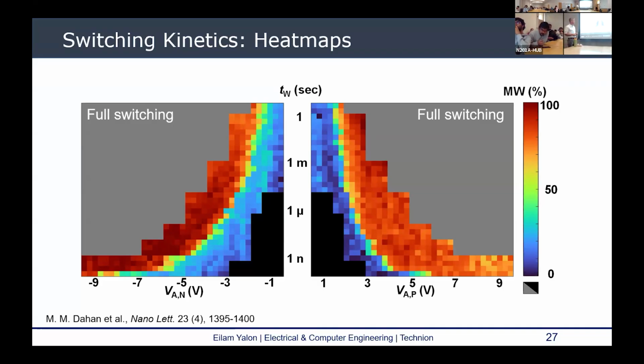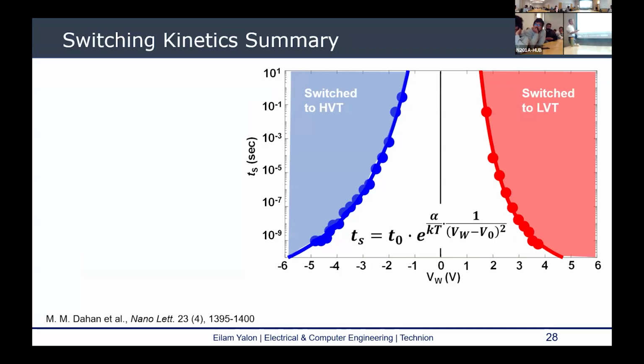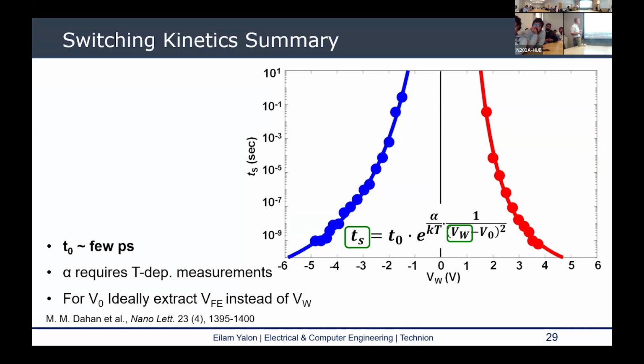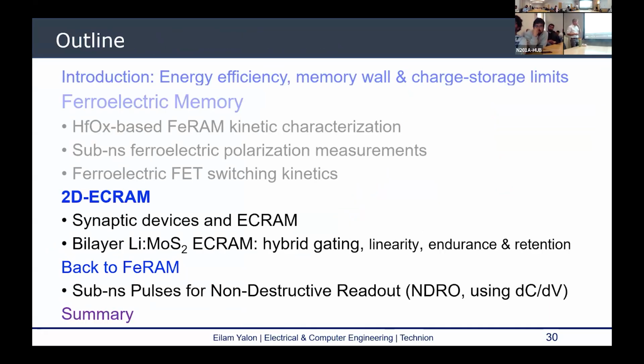And you can see this switching kinetics across more than 10 orders of magnitude in time. We can assign a switching voltage at the 50% memory window. We then plot the switching time versus voltage. Again, we use this simplified nucleation switching model to fit the data and extract some information. So in this case, with a smaller area, the extracted minimum switching time is a few picoseconds. And the switching kinetics is fairly simple.